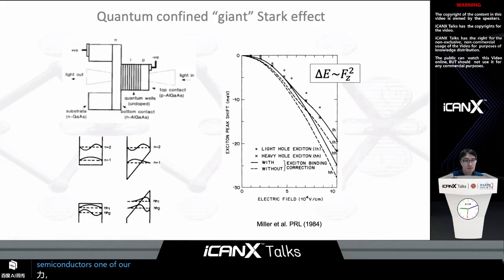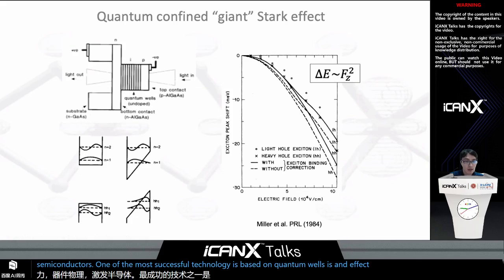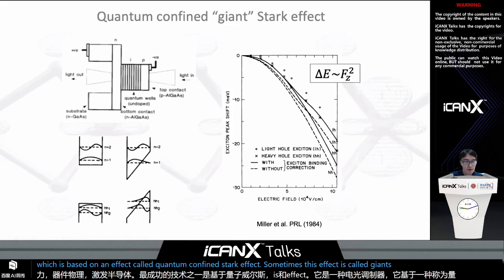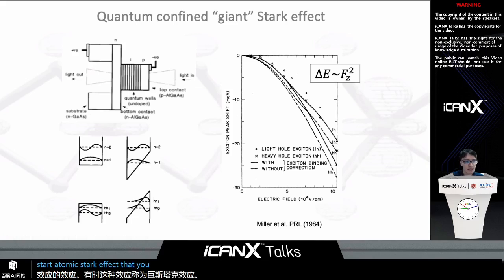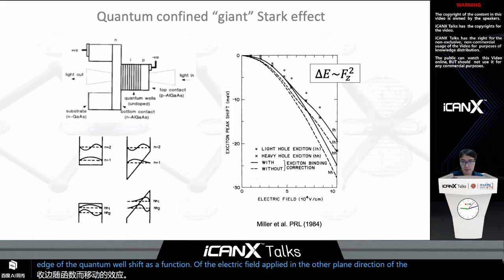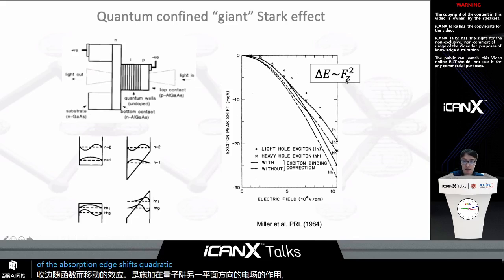One of the most successful technologies based on quantum wells is electro-optical modulators, which is based on an effect called the quantum confined Stark effect. Sometimes this effect is called the giant Stark effect, to contrast with the atomic Stark effect that you normally study in undergraduate quantum mechanics. But this is an effect where the absorption edge of a quantum well shifts as a function of the electric field applied in the out-of-plane direction of the quantum wells. And the energy of the absorption edge shifts quadratically with the electric field. The reason it shifts is because of the polarization of the electron hole pairs in the quantum well, and the shifts in their energy levels due to the electric field.